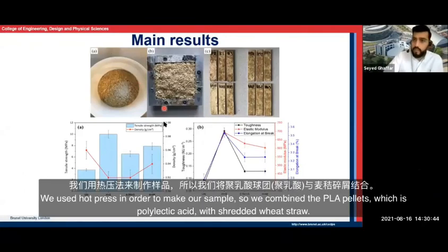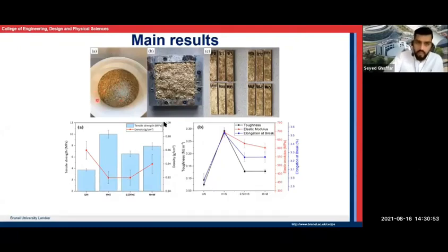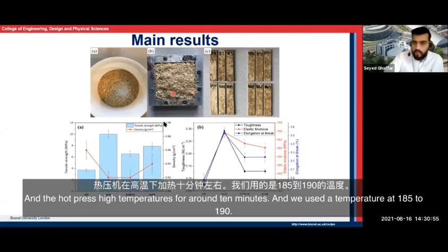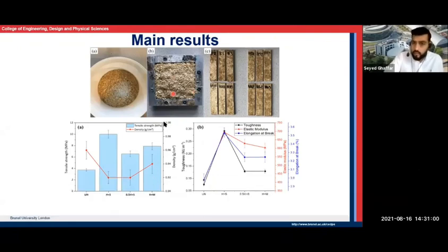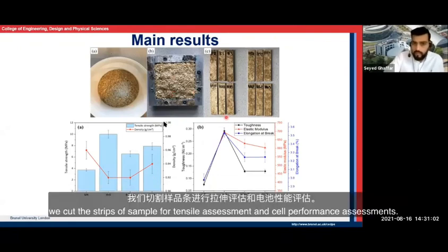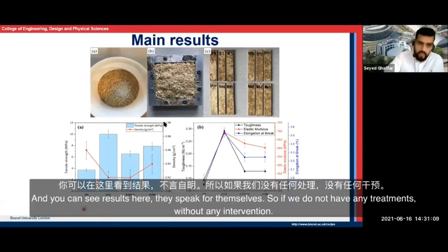We used hot press in order to make our sample. We combined PLA pellets, which is polylactic acid, with shredded wheat straw. And we hot pressed it at high temperatures for around 10 minutes, using a temperature of 185 to 190. We cut the strips of sample for tensile and cell performance assessments. And you can see the results here.